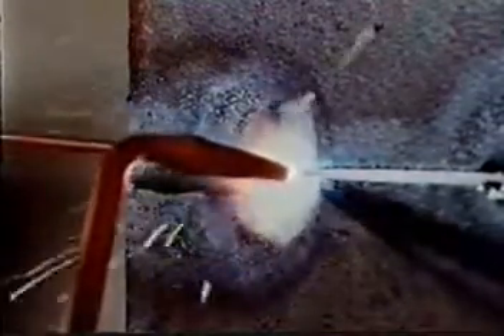The tip of the cone is held close to the surface at approximately 90 degrees to the weld, ensuring even melting of both edges with good root fusion and penetration. Notice the smooth, rhythmic motion of the rod, evenly distributing metal over the sides and root of the weld to produce a finely rippled bead, blending smoothly with the parent metal.